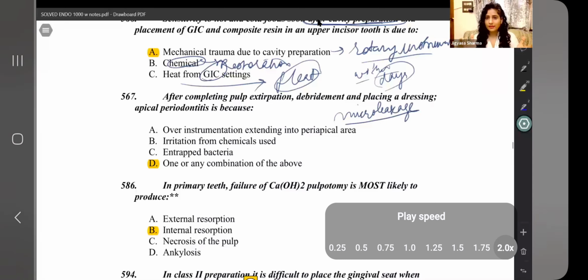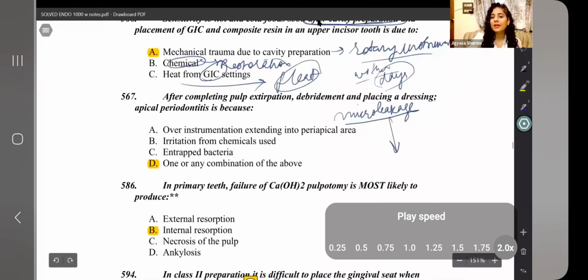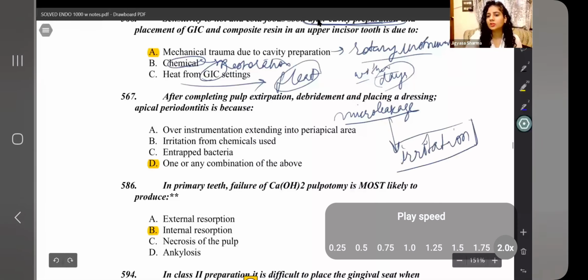But if it is not getting relieved, it is not reversible, and it's worsening beyond a few days and weeks, then it is leading to irreversible damage, and that means there is continuous insult, and the continuous insult is coming only from your microleakage, because mechanical trauma would have subsided, and the pulp would recover from that, and from irritation from the restoration. But it's the continuous leakage and continuous irritation from the bacterial fluids or the bacterial contaminants in oral fluids. So continuous irritation is most commonly from the source of microleakage.